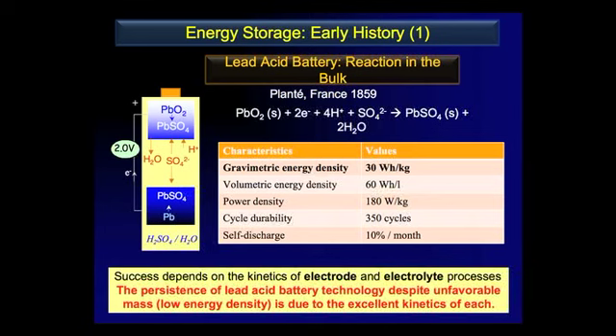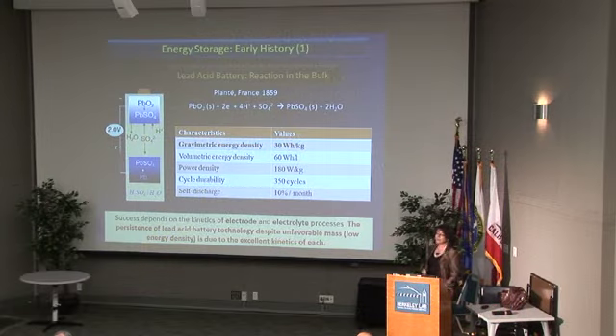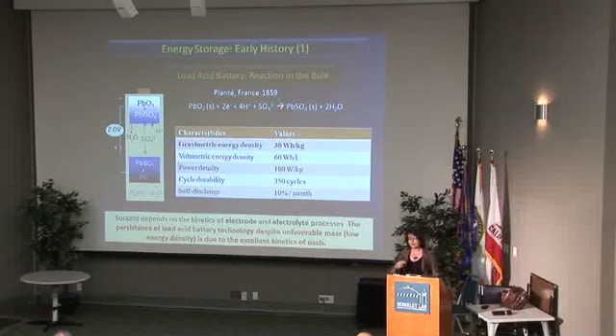And effectively, it's the conversion of lead to lead sulfate or lead oxide to lead sulfate, which drives the EMF difference between them, which drives the reaction. And of course, sulfuric acid is an electrolyte. And that has a pretty poor gravimetric energy density, and some of these numbers will come up again, so perhaps keep them in mind. So this is 30 watt-hours per kilogram with a volumetric energy density of 60 watt-hours per liter.